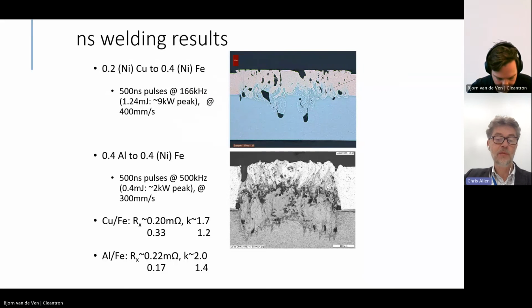So this is some similar information now from welds made using this machine gun-like or nanosecond pulsed laser. So it's a different type of laser. The welding parameters are quite different, but look at the welding speeds, and these are not a million miles away from the welding speeds that we can achieve using the other type of laser. So from a productivity point of view, these two types of lasers are competitive. And again, if you look at the electrical information at the bottom of the slide, you can see that once again, the aluminium to steel welds are, not surprisingly, that bit more resistive than the copper to steel welds in relative terms. Next slide, please.